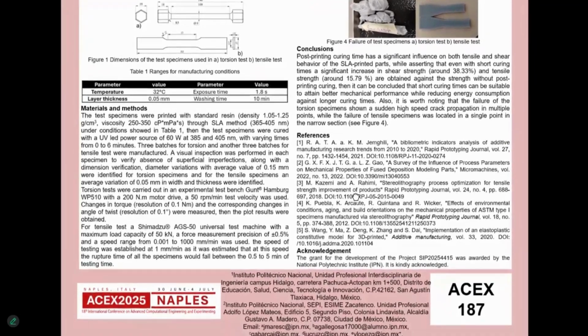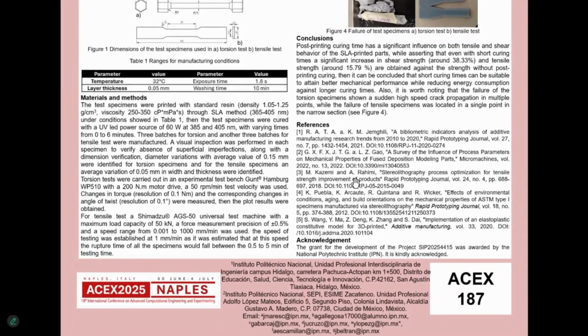The ASTM E143 and the ASTM D638 standards were used as guidelines for the torsion and tensile tests respectively. Torsion tests were carried out in an experimental test bench Gunt Hamburg WP510 with a 200 newton-meter motor drive at 50 RPM test velocity, while the tensile test was made with a Shimadzu AGS 50 universal test machine with a maximum load capacity of 50 kilonewtons and at a speed of 1 millimeter per minute.